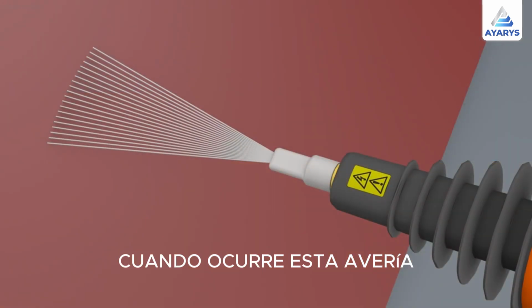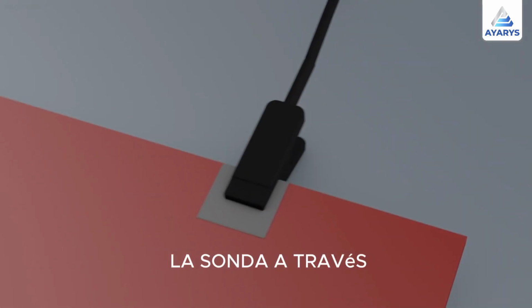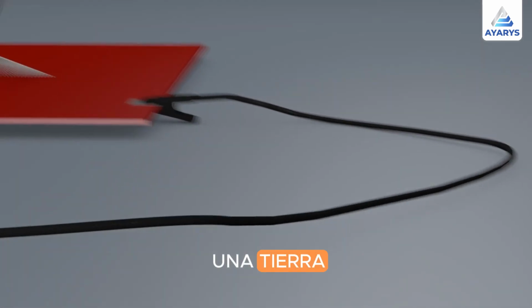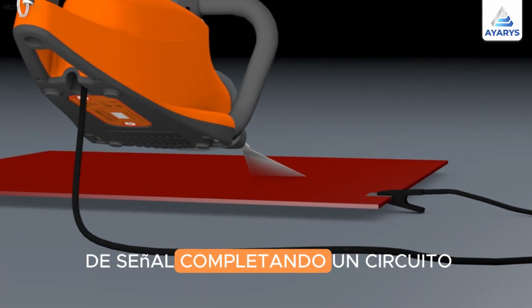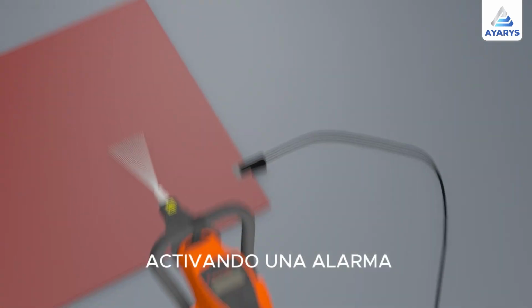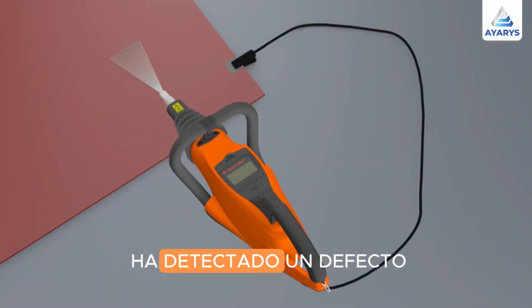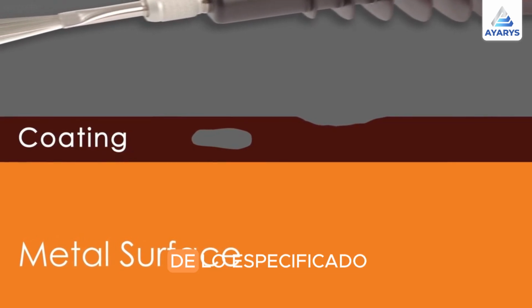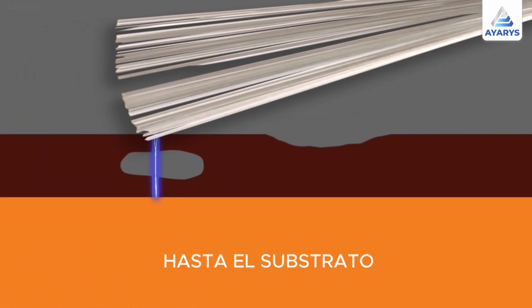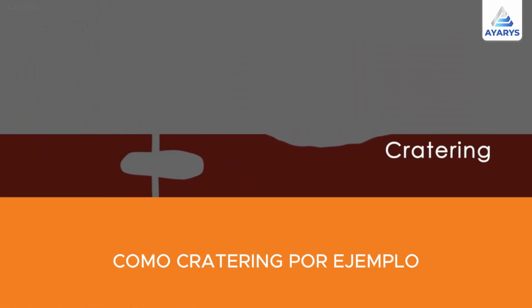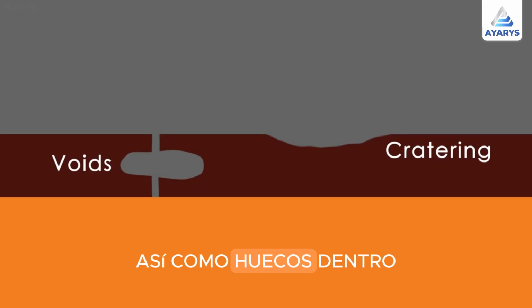and the substrate. When this breakdown occurs, the current flows from the probe, through the substrate, and back into the holiday detector via an earth or signal return cable, completing a circuit and thereby triggering an alarm to signal a flaw has been detected. As the high voltage method can locate any area where the coating is weaker than specified, this method allows you to detect flaws that don't go all the way down to the substrate, such as cratering for example, as well as voids within the coating.